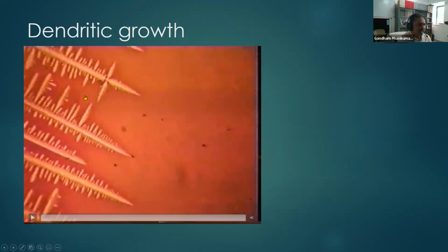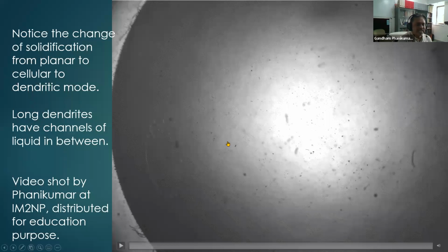The intermediate interdendritic liquid will solidify and lead to full solidification. And sometimes if the liquid was not enough, it cannot come in. Then you see a defect called cracking. Hot cracking will occur. So we will come to that. Now, how does the pattern formation actually happen during solidification?